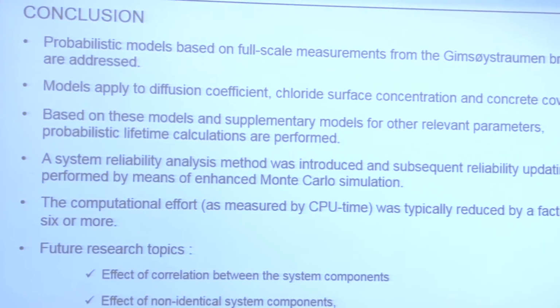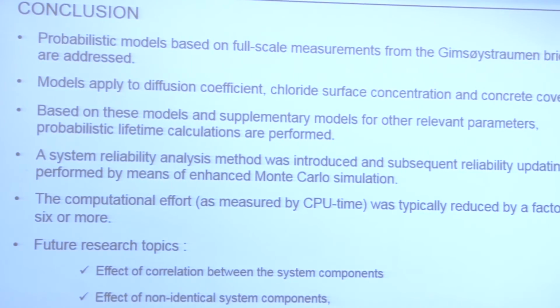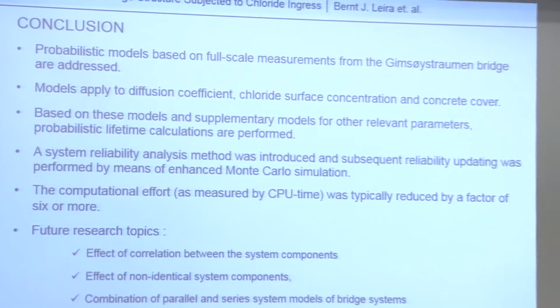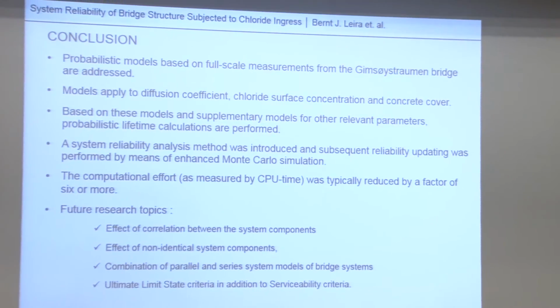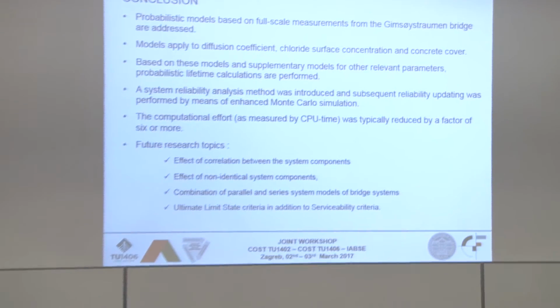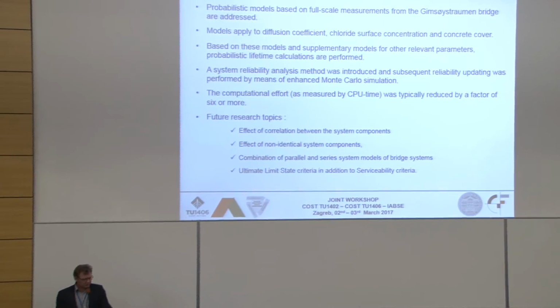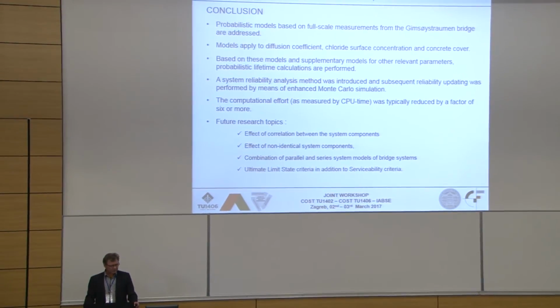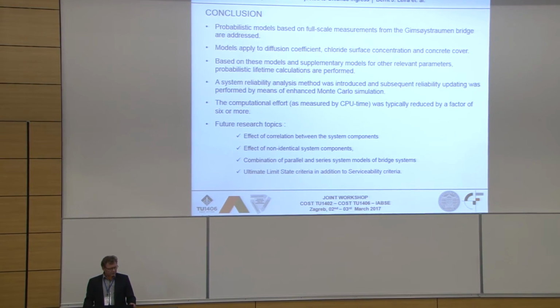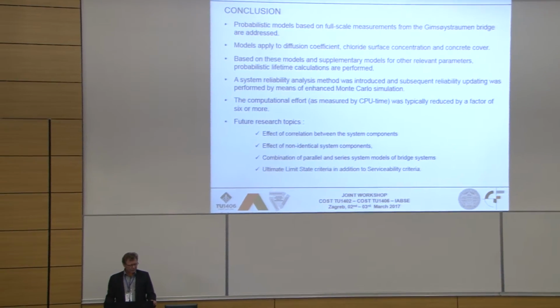Also, we performed probabilistic lifetime calculations for a single site to start with, and then we looked at system reliability effects by an enhanced Monte Carlo simulation method, which has also been applied to other system models for other applications previously and found to be stable and efficient. Computation time is typically saved by a factor of 6 or more.